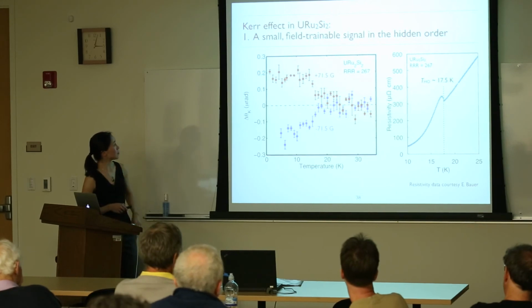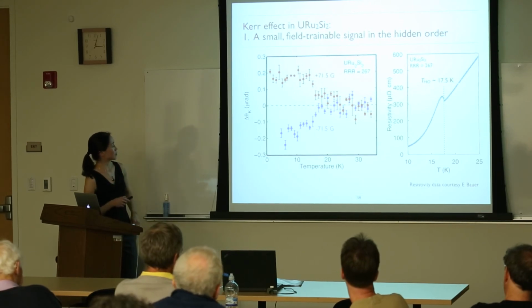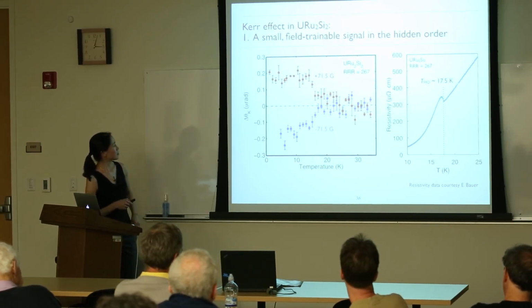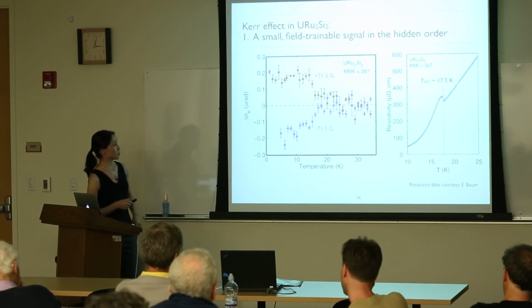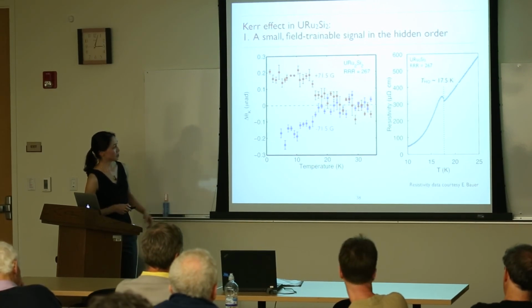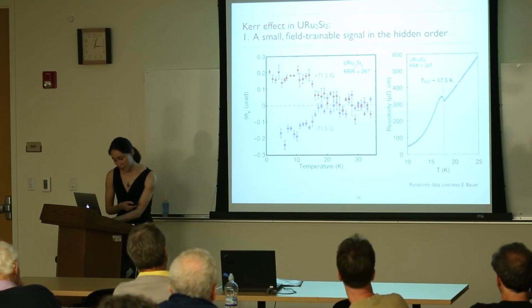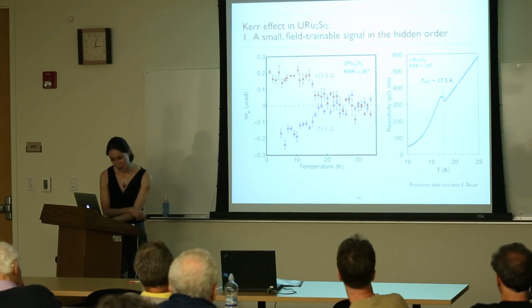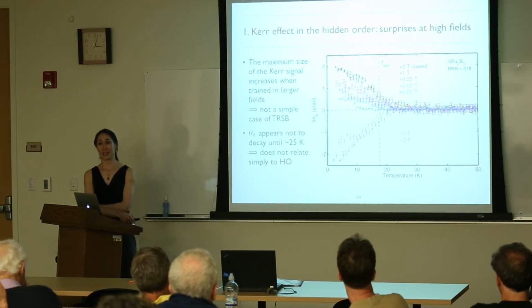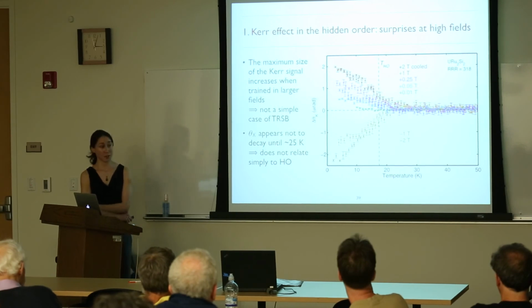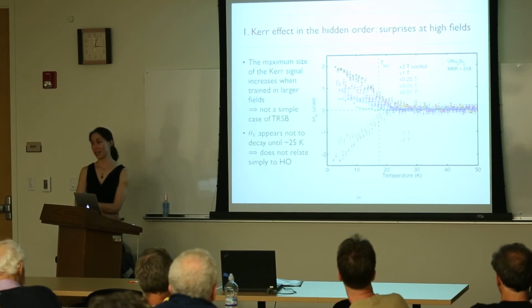So what we see in the hidden order, again at around 17.5 Kelvin, is a small field trainable signal that we're able to see here. This is resistivity data from the same crystal, so we know where the hidden order transition is. At first we thought, okay, this is a case of time reversal symmetry breaking, but it turns out that the picture is a lot more complicated than that.